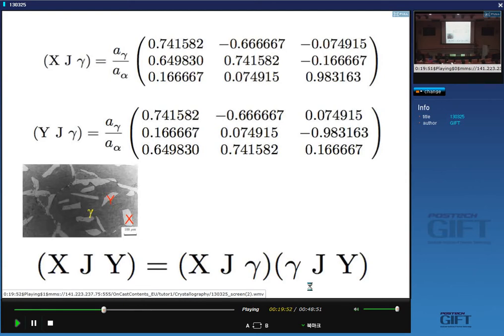Exactly. So one reason is if you have planes which are almost well matched, then the interfacial energy will be small, right? And if you have close-packed planes which are parallel and close-packed directions within them which are parallel, then you're likely to get good fit between the two crystals, right? Now, why is interfacial energy important? Why should we want to reduce the interfacial energy? Yeah, because by the time you've seen the crystal, the surface to volume ratio is really very small. So why is it important that the interfacial energy has to be very small when we get a transformation in the solid state?